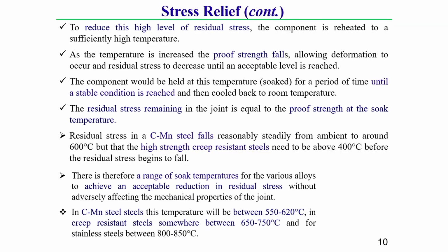Now, in this stress relief related things I will discuss a little bit more in detail. So, to reduce this high level of residual stress in weld specimen, the component is reheated to a sufficiently high temperature. This temperature, though it is high, is below recrystallization temperature, this you should keep in mind. At this temperature, as the temperature is increased, the proof strength falls, which allows deformation to occur and residual stress to decrease until an acceptable level is reached. This you should keep in mind. This residual stress decrease we generally consider to an acceptable level by holding the soaking time.